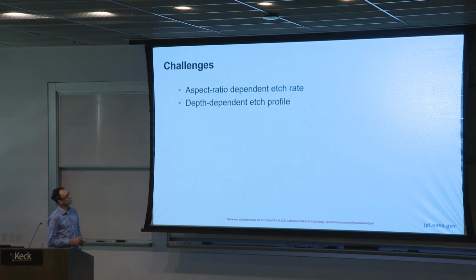Another thing that can be very annoying is that you can have a depth-dependent etch profile. Even if you have done a good job for a certain type of etch, so let's say you designed an etch that was supposed to be 10 microns deep, now someone tells you, oh, you can do 10 microns, let's do 100 microns. And you happily agree, and you just try to do this for 10 times as long, and what typically will happen is that your etch profile, instead of being perfectly vertical, will start tapering off, and at some point it cuts off your features and they're not there anymore. That is also possible to address, but it is also aspect ratio dependent, so it's hard to completely solve this for the entirety of a metasurface where you're mixing very small and large features and large and small gaps at the same time.